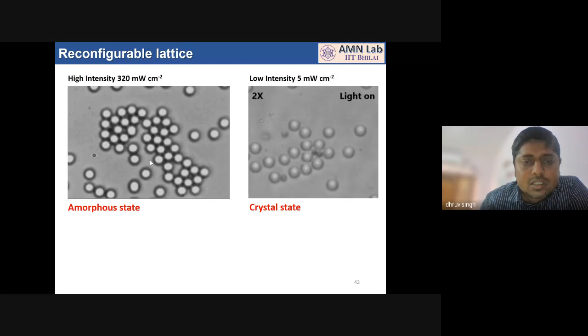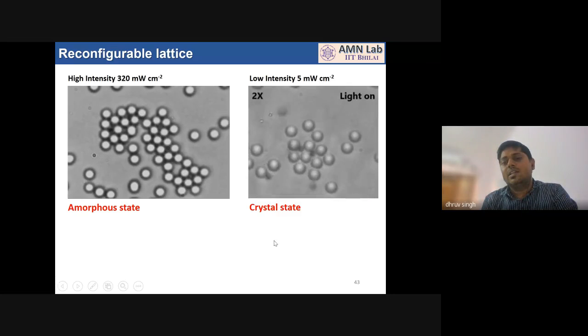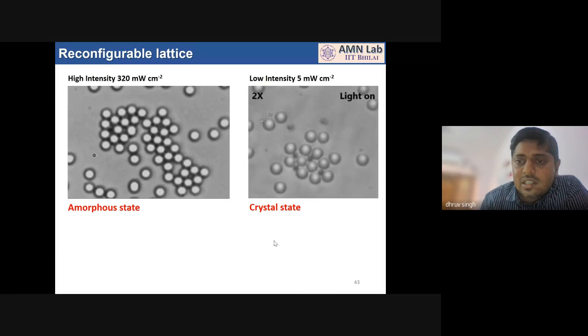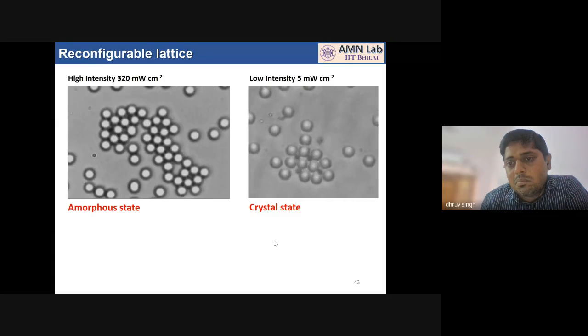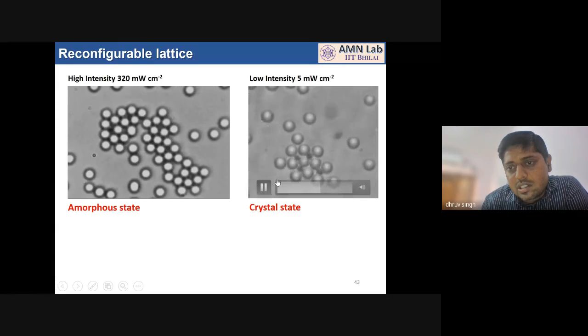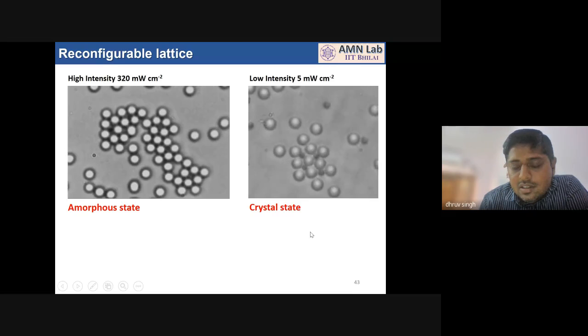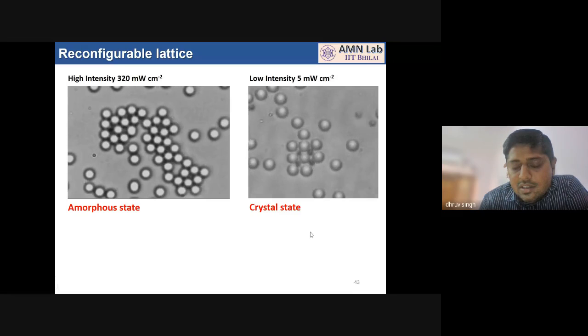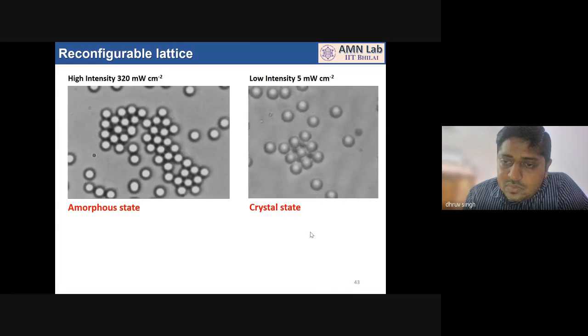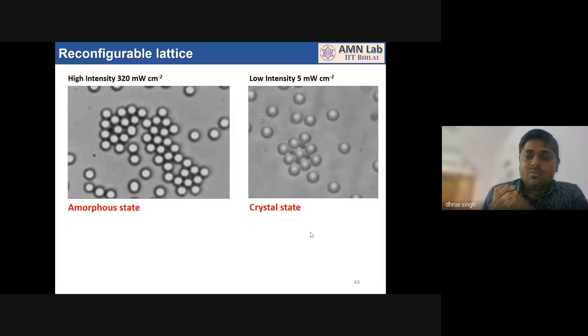It was not preserved. But if you grow the assembly at a lower light intensity such that the interaction between the active nanomotor and passive particle is possible, no particle can attach in the second layer, then you end up with a perfect square lattice. So in this way, with the same set of particles, by just controlling the intensity of light, that means dynamically, we can control the lattice order of the structure.